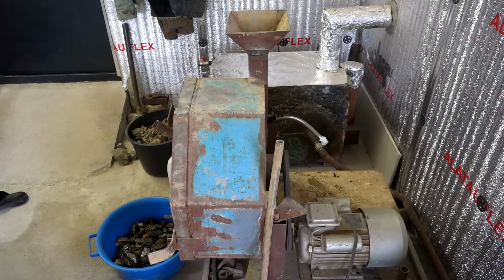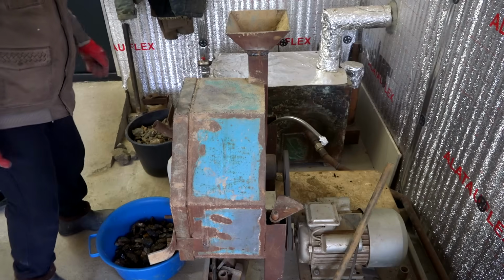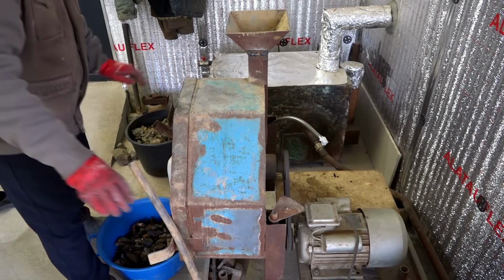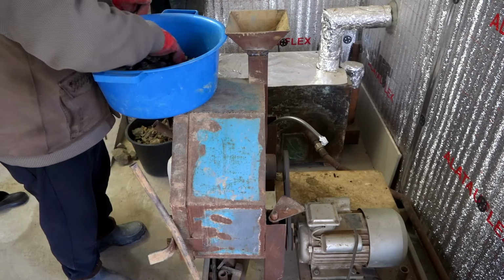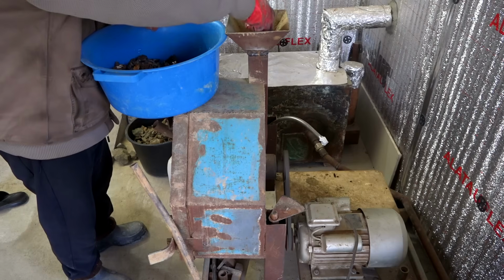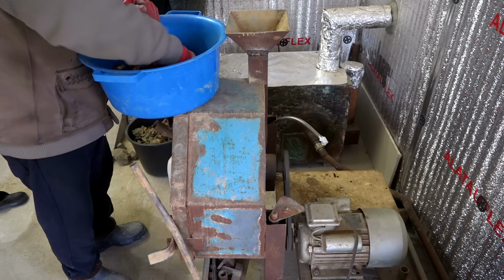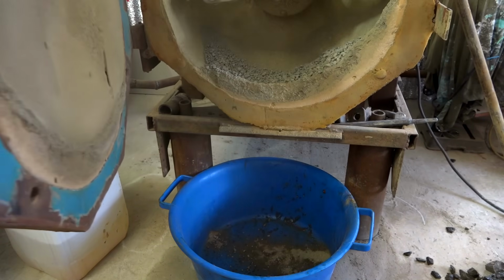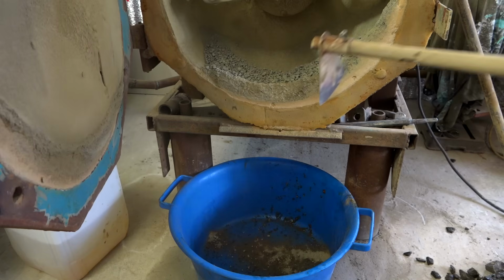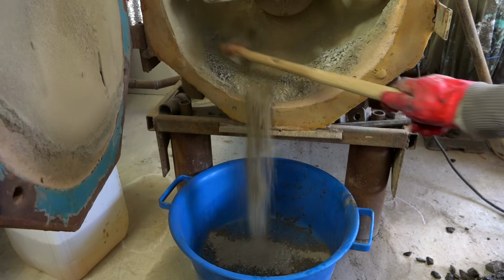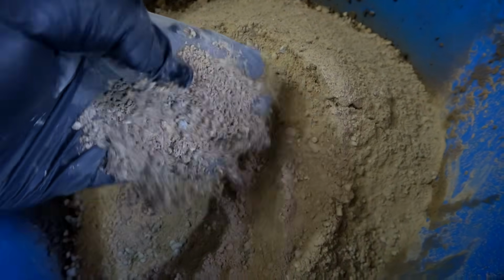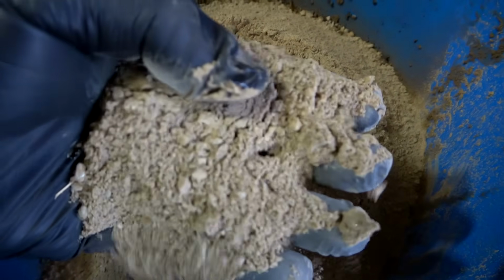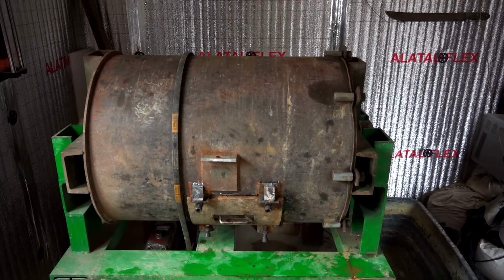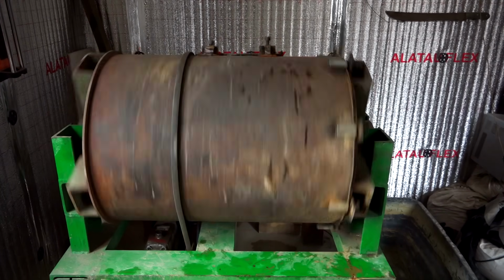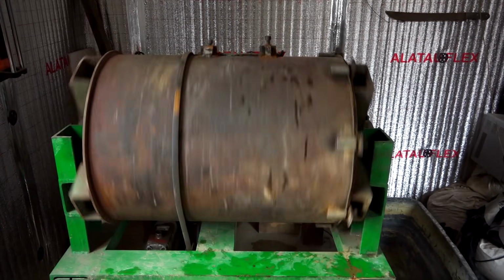I pre-wet the stone with water to prevent dust from forming. This is just preliminary crushing. Next, I fill the rod mill more than halfway with crushed material and run it for 2 hours. This is enough time for the pre-crushed material to turn into pulp.